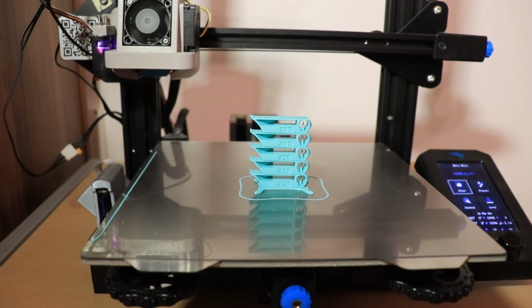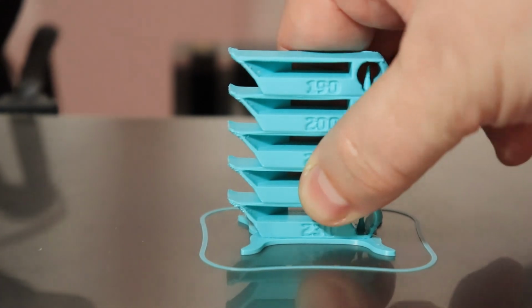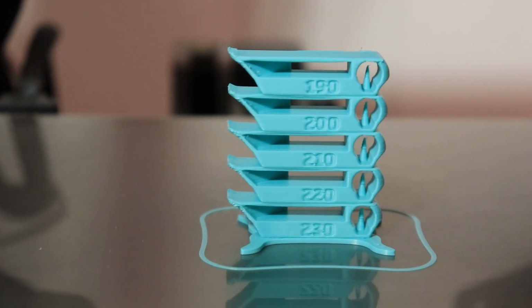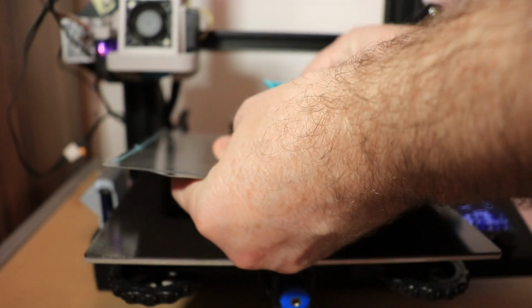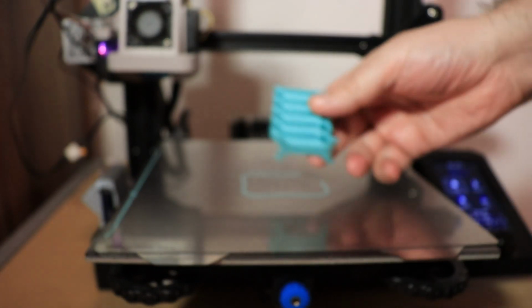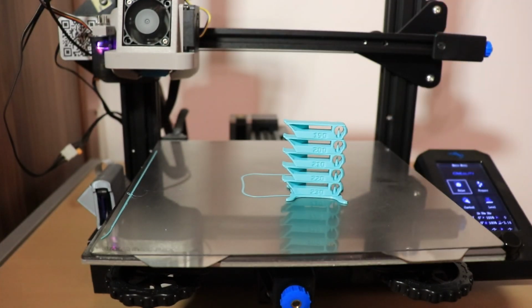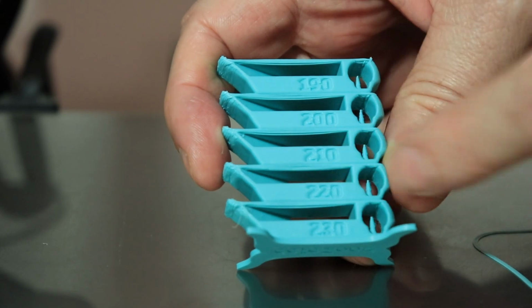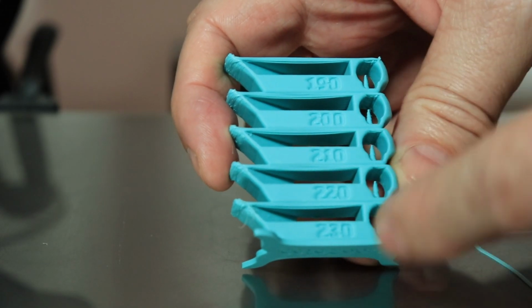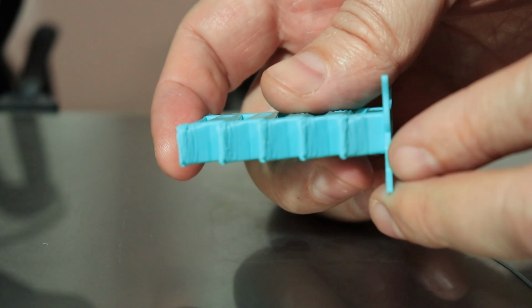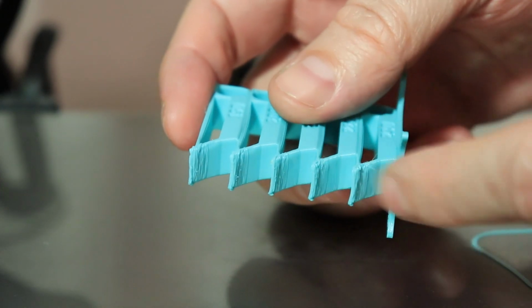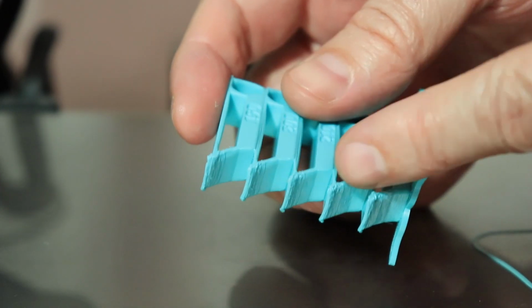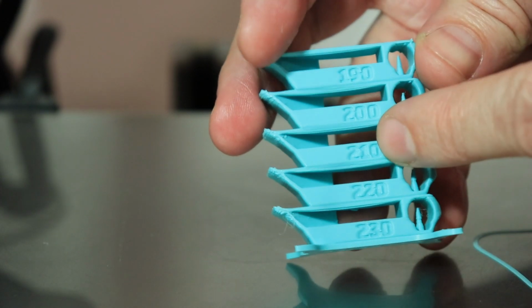Printing is finished. Let's check the bed adhesion. Okay. Actually not a bad temperature tower. The bridging came out perfectly, no stringing at any temperature. The only problem I can see is on the overhang at these two highest temperatures, but these three are quite acceptable, but everything I will print at 210 degrees Celsius.